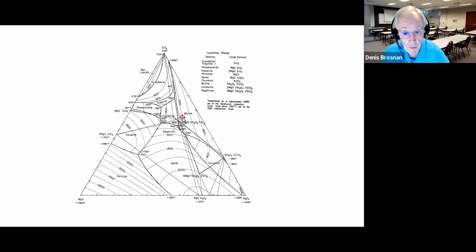and there are some cordierite polymorphs. One is called indialite, the other cordierite. Nevertheless, if you're right on the money of the composition, you're going to have 100% cordierite. But if you miss the composition a little bit, you can have mullite show up. You can have crystalline silica show up. You can have enstatite show up. Forsterite show up. These are minerals over here in the magnesia silica phase diagram. You can have mullite show up, and you can then go down here and have magnesium aluminate or magnesia spinel show up. So the idea is that if you hit this composition right on the money, you're going to be at the lowest thermal expansion coefficient.